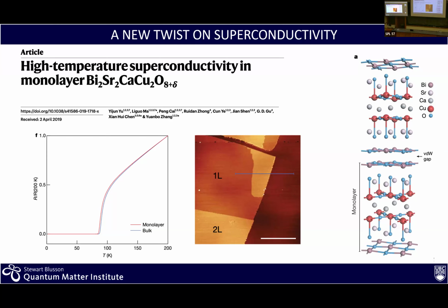And here you see the resistance versus temperature for 2 systems. One is the bulk superconductor, and the other one is the monolayer. And then you can see they're exactly the same. This is a major achievement as far as fabricating a single monolayer superconductor, the single layer. It's extremely difficult to get it and not damage it, not lose oxygen that will kill superconductivity. But what is remarkable is the demonstration that superconductivity is really 2-dimensional in these materials. We already knew that to a very high degree, but this is a very visual and practical demonstration of this fact. Superconductivity lives in the single layer in cuprates.